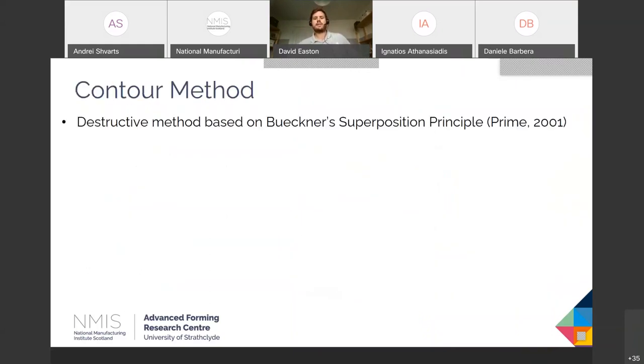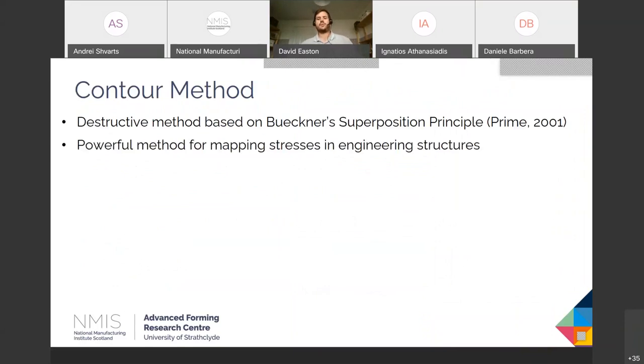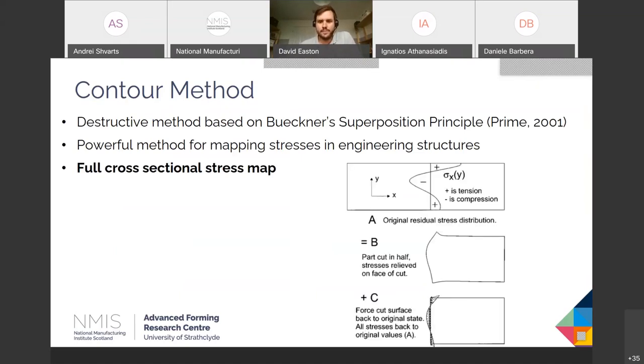The contour method, so this is when we're starting to look more in the bulk of material. And this is quite a new method. It was invented in about 2001. It's based on Bueckner's superposition principle for any fracture mechanics people out there. And it's a very powerful method for mapping stresses in engineering structures. The premise behind it is we can take a part, we can cut it in half, and the part's going to deform. By measuring that surface deformation, that surface contour, we can calculate what stresses it would take to force it back to a flat condition. And that essentially gives us the residual stress in the part.